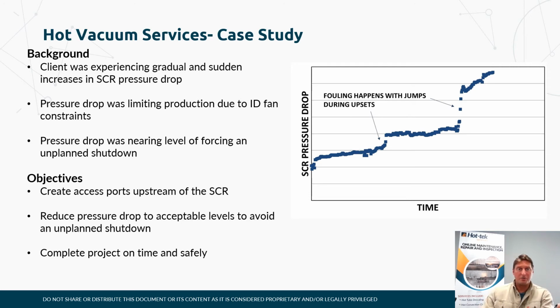So our case study here that we're going with, we see a significant SCR pressure drop due to fouling and upsets. We were extremely close, by the time we moved on site, to moving into a forced unplanned shutdown due to the ID fan constraints and possibly tripping due to the amount of stress that those fouled screens were causing.